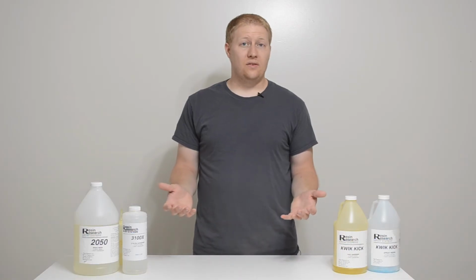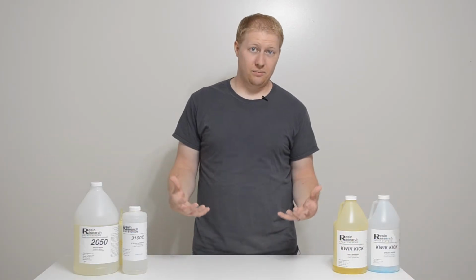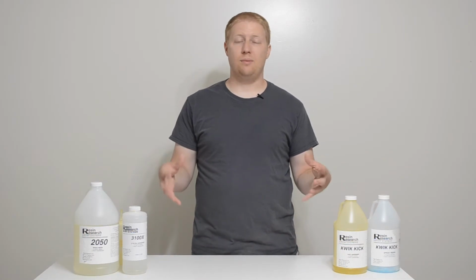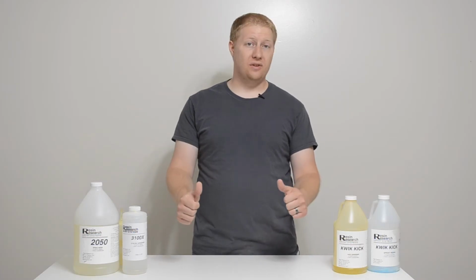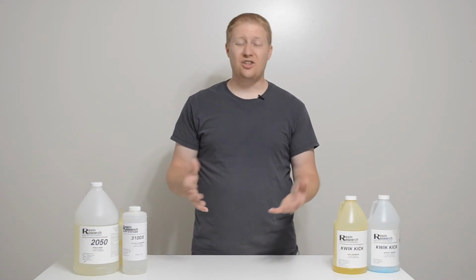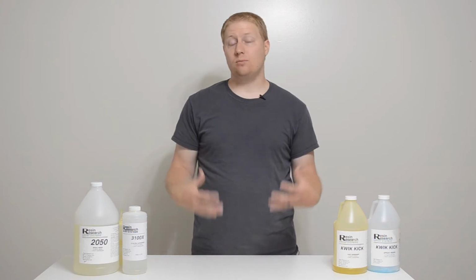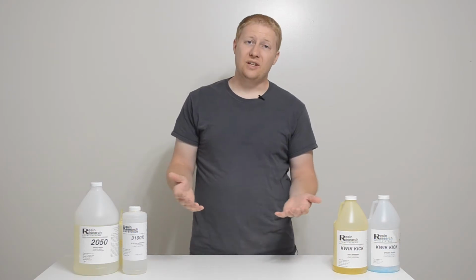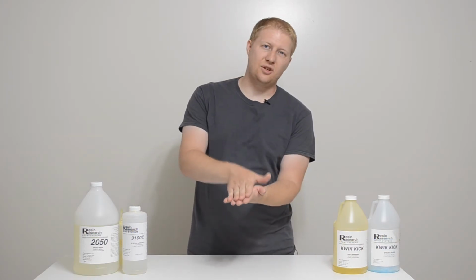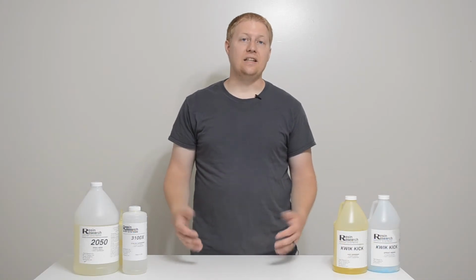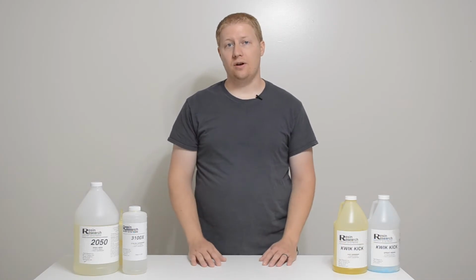Really all an autoclave is, is a big pressure cooker. Generally it pumps the pressure in the chamber up to about 60 psi while you're pulling vacuum on the part, so all that pressure compacts the layup, which makes it a more efficient structure. It also gives better strength between the plies so they don't peel apart quite as easily. The other thing that an autoclave does is it adds heat, so you have an elevated temperature cure. Again, for a room temperature resin, you don't necessarily need an elevated temperature for it.